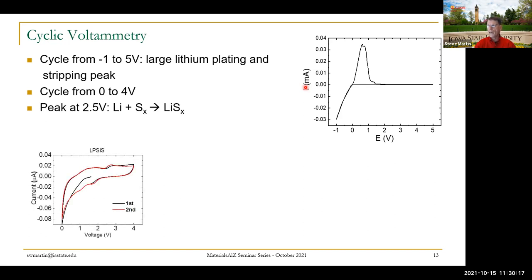And when we do that, now we're at a 1,000 times finer scale. We're in the microamp range. There is no peak here because we're now looking slightly above 0 volts and more positive. If we go to lower negative voltages, all we do is just plate and strip and it dominates everything. So we start slightly above zero so we can just see the electrochemistry. We know they're stable in contact with lithium metal. Let's look at higher voltages.